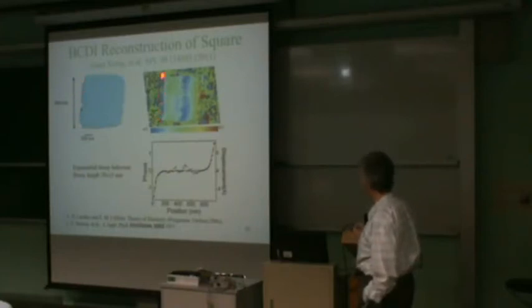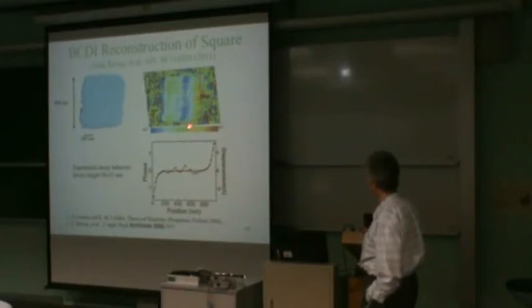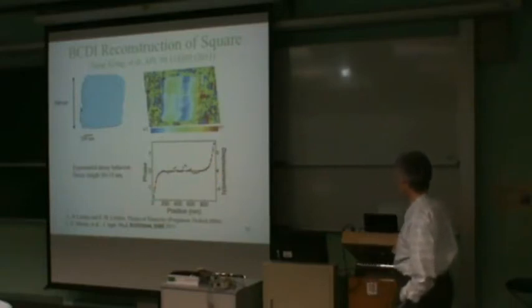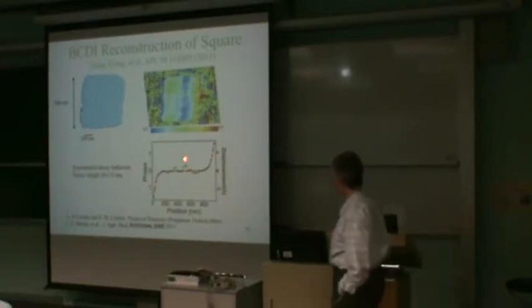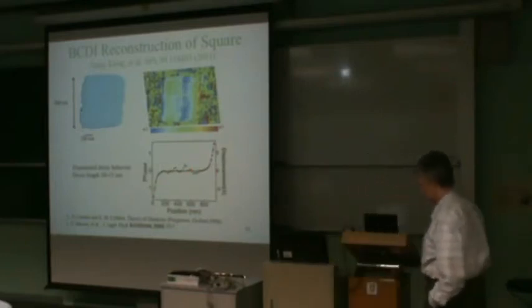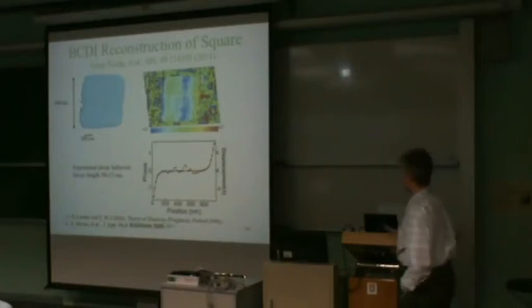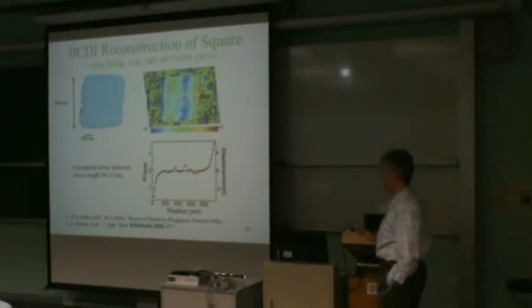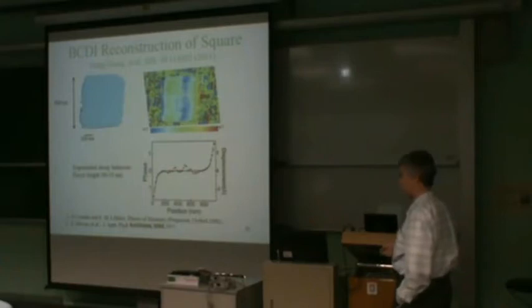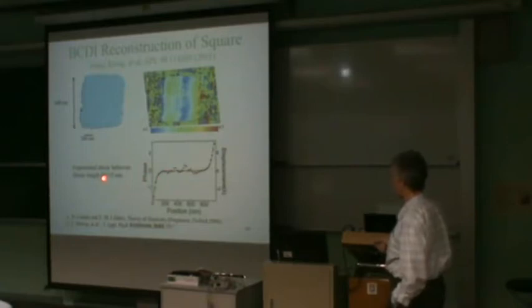But there's a clear pattern of strain inside that structure, and you can see one edge of the crystal is going in the red direction, the other edge is going in the blue direction. If we take a line through it, you can see that there's a clear relaxation of the silicon at one end and at the other end in opposite directions. And the fit is just to a straight exponential. I noticed in Connell's talk just before that I think you had a cosh function as the expected function for this, so it will be exponential at the two ends, if I'm correct. And the decay length is 50 nanometers for this.